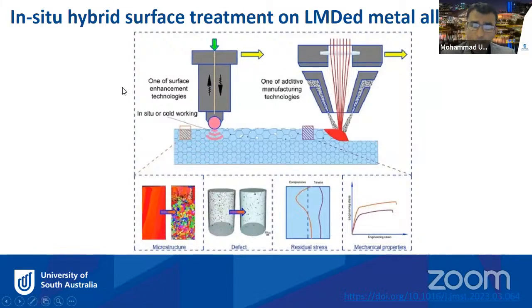Okay, so these are the treatments I have just shown you earlier. These are offline: you make a sample and you do the treatment later on, right? However, nowadays the in situ hybrid surface treatment is growing, because it is very important in the case of laser metal deposited alloys. So for example, this is the metal deposition process, and then generally after the metal deposition,